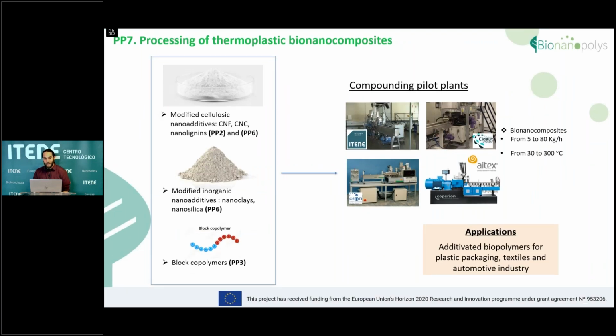Regarding pilot plant 7, all of these modified cellulose or nanoclays or the block polymers we obtained from pilot plant 6 will be compounded in one of our different extruders available. Those are twin screw extruders to allow better mixing of the materials in the polymers. And we have capabilities from 5 to 80 kilograms per hour, and from 30 to 300 degrees Celsius. And from the project, we will select which equipment is better suited for each application, depending on the final purpose of your applications.